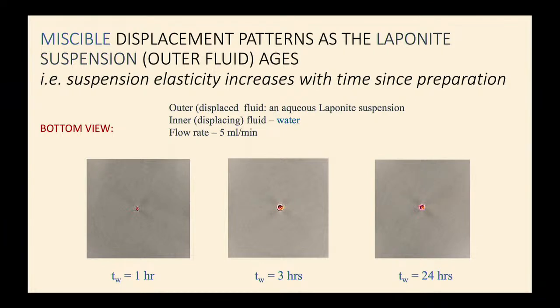In the second system, so these are all separate experiments, we introduce the clay and wait for 3 hours. Now the structures have started building up, though they are not very dense yet. So this is elastic, but there's also a viscous component that is quite significant. But after 24 hours, it's like our window glass. It's a solid. Like I said, I can't reiterate this enough, these are systems with memory, they are aging.